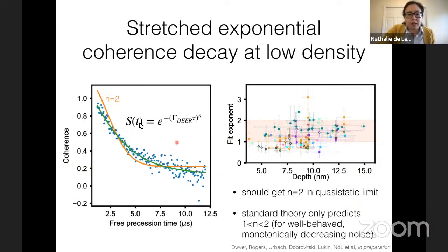The second puzzle is that if we tried to fit our free induction decay signal, so this normalized DEER signal, very carefully, what we found was that it did not fit well to the form that we expected. So in general, you can just write down that if you have a quasi-static bath, this free induction decay signal should look like e to the minus (gamma tau) to the n, where this n is exactly 2. But you can see that if we try to fit this to an n of 2, this is the best fit, and that provides a really poor fit to the data.